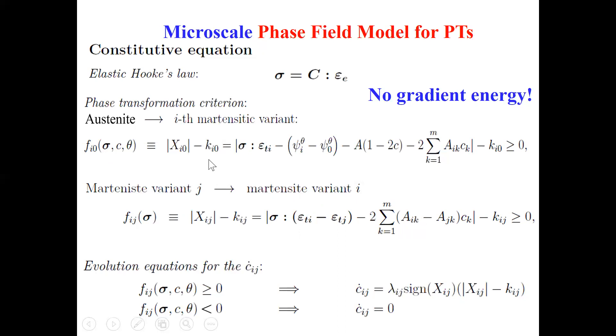We also introduce a thermal threshold. It's not easy to introduce it in nanoscale phase-field approaches, though we have developed several methods. Here, like in micromechanical theory, we introduce a thermal threshold: if the driving force exceeds the threshold, we prescribe a simple linear kinetic equation between the rate of interface change and the net driving force — driving force minus the thermal threshold. Now, if we want a scale-free theory, we must avoid gradient energy.